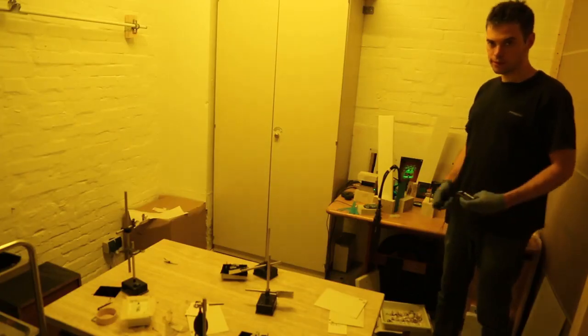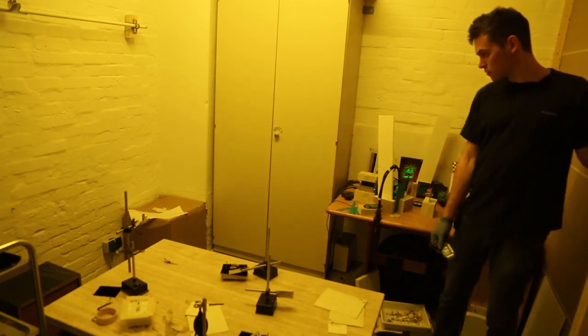DCG is very forgiving to overexposure. One can expose 10 times longer than actually necessary and still get a good hologram. Perfect conditions for making DCG holograms is warm and dry. You want the humidity to be around 60% and the temperature at around 24 degrees. The room temperature is the key factor. The colder it gets, the harder the gelatin becomes and the more light power you need to make the hologram. Below 10 degrees, it becomes very difficult to shoot DCG holograms at all.